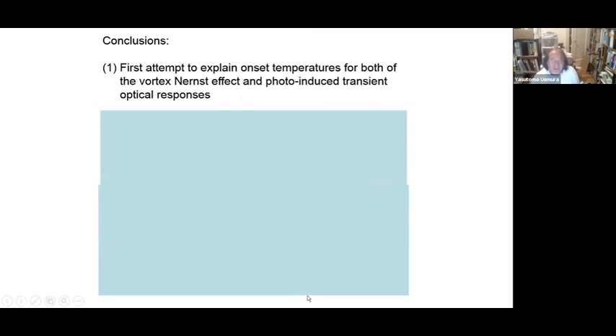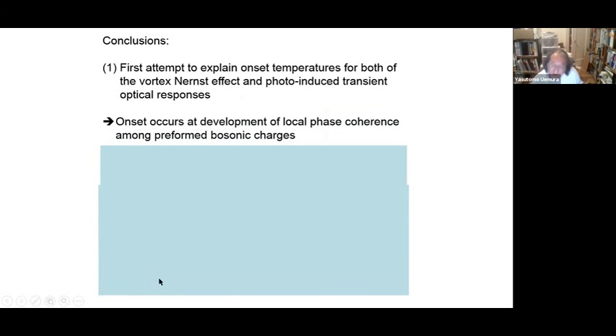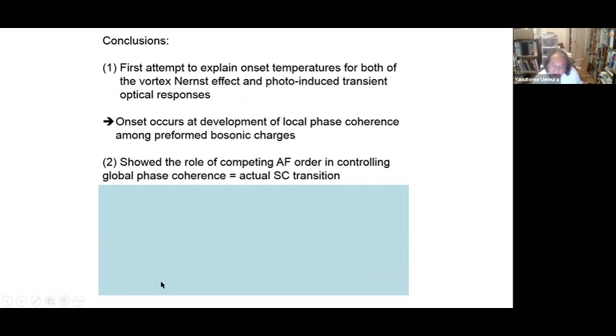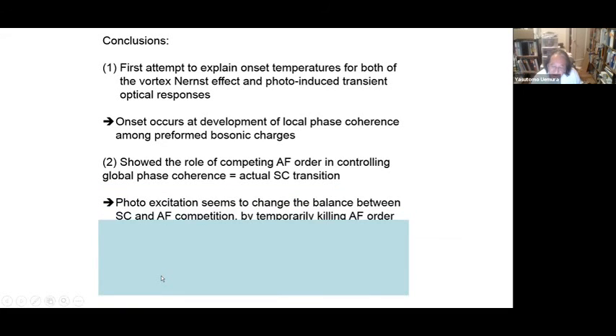I'm sorry for overtime, but this is my conclusion. I showed a first attempt to explain onset temperature for both the vortex Nernst effect and photo-induced transition, transient optical responses, and onset occurs, in my opinion, at development of local phase coherence among preformed bosonic charges. And I showed the role of competing antiferromagnetic order in controlling global phase coherence and the superconducting transition. And photoexcitation seems to change the balance between superconducting and antiferromagnetic competition